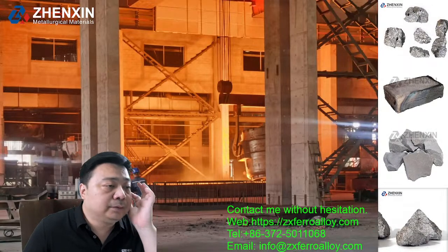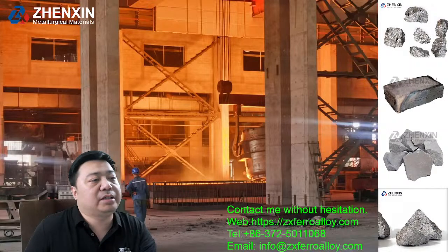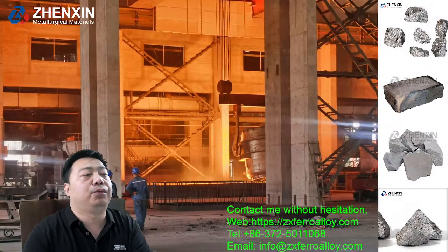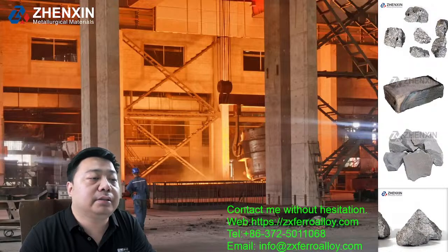When the charge temperature is more than 2600 degrees, the already produced SiC will be partially decomposed, and the decomposed silicon will form SiC again with the C in the charge.